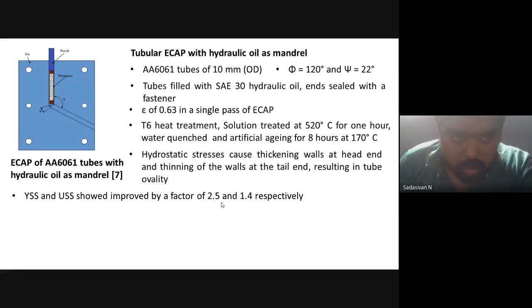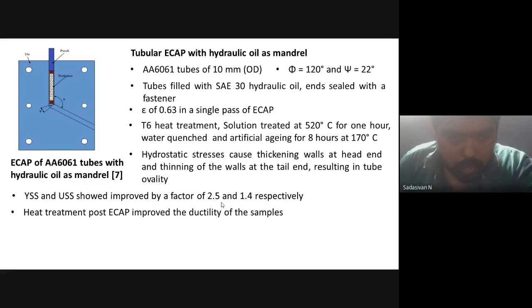So the testing of this material was carried out. The torsion test was carried out, because a tensile test was not done in this particular work. Yield shear strength and ultimate shear strength improved: some 250% improvement in yield, and 140% improvement in ultimate shear strength was found after this ECAP. Heat treatment further improved the ductility of the sample.